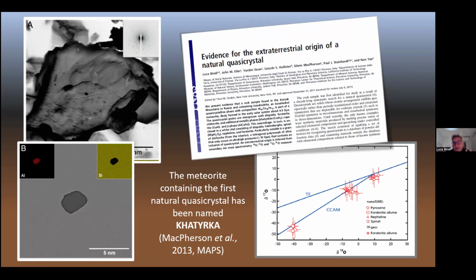So this was a very important point. Also at that time, to rule out the possible anthropogenic origins, because of course stishovite is not found in classic metallurgical products. Another piece of evidence we reported at that time was the measurement of the triple oxygen isotopes, which are reported on the bottom right, where you can see that all the data obtained on the oxygen-bearing materials coexisting with the quasi-crystals fall on the CCAM line, just indicating that, of course, they are extraterrestrial in origin.